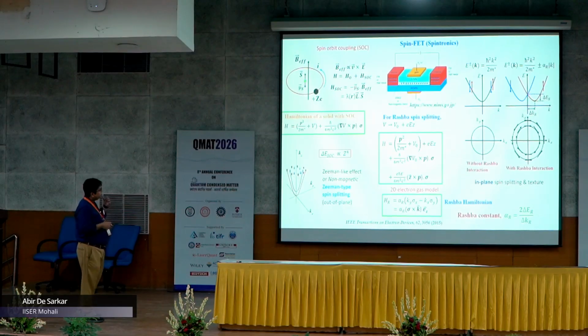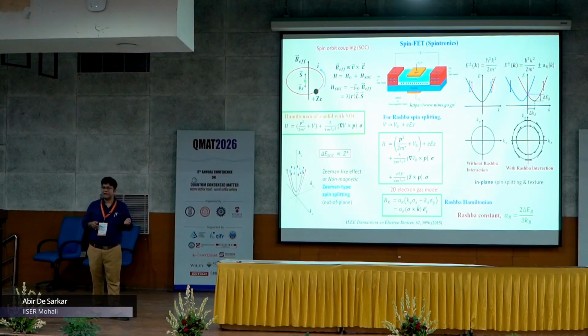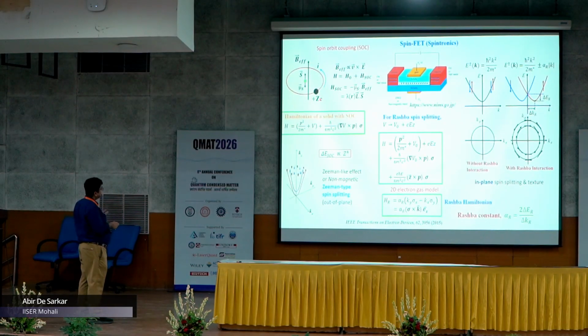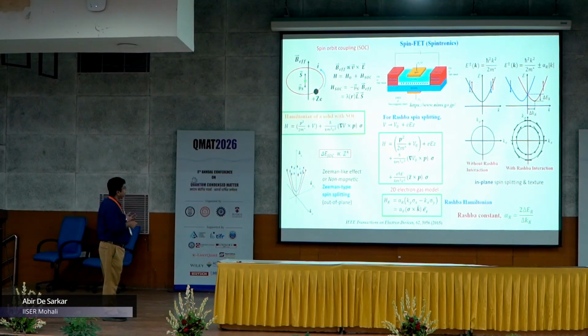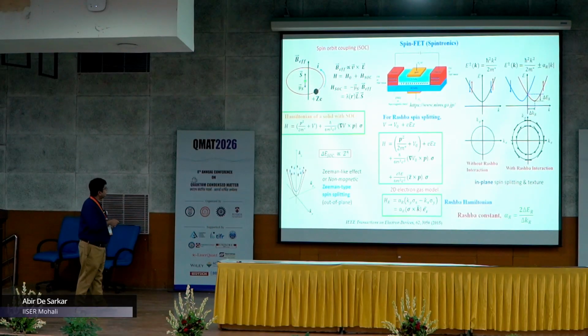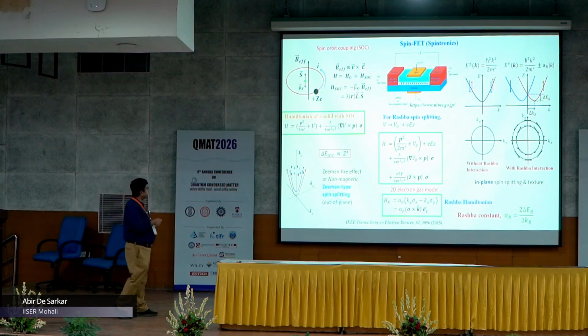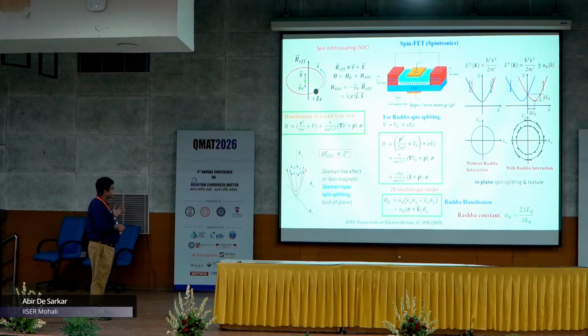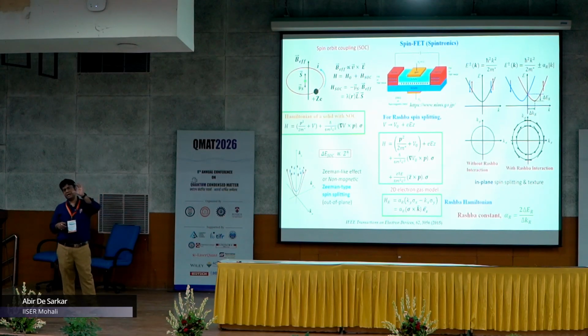Before I present our work on Janus structures, I need to talk a bit about the spin-orbit coupling. Now, spin-orbit coupling naturally arises in a material containing one or more heavy elements. Then the spin-orbit coupling acts as a perturbation to the main Hamiltonian, and it brings about a Zeeman-like spin splitting, an out-of-plane Zeeman-type spin splitting. The heavier the element, the higher is the Zeeman-type spin splitting, the higher is the spin-orbit coupling.